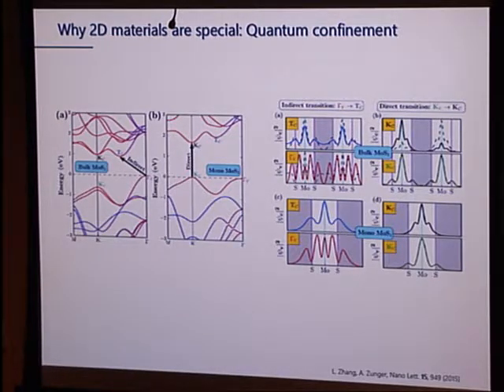Why is that? Well, it has to do ultimately with quantum confinement. If we look at the wave functions in bulk MoS2, then at the gamma point, you can see there's a significant amount of electron density that is between the sheets. But at the K point, not so much. And then what happens as we go to the monolayer is that at the K point, this by and large stays. But now at the gamma point, where you are somehow terminating this wave function, this introduces a large effect, and that drops the gamma point down such that the K point suddenly becomes the valence band maximum. That, at least, is the current understanding. It's still maybe marginally contentious, but generally people believe that.